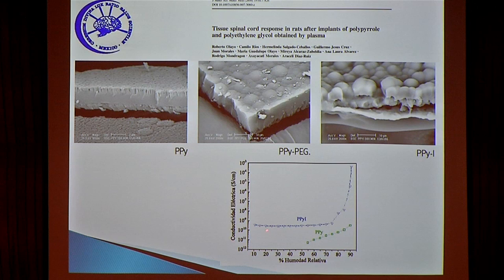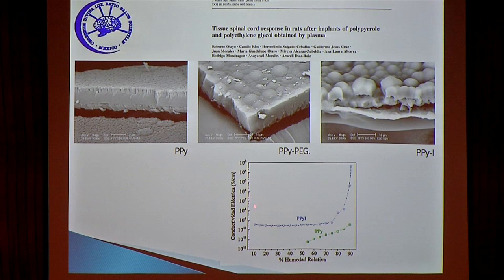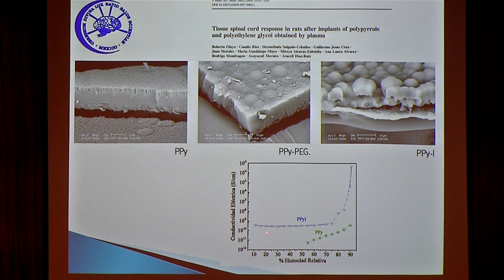So this is the electric conductivity at different percent of moisture in the environment. And you can see these are siemens per centimeter. And you can see how the conductivity depends on the relative moisture of the measurement. And after 70% of moisture, the material became very conductive.